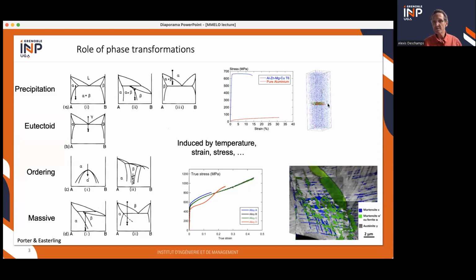Just two examples. If you make nanoscale precipitates, these are very efficient obstacles to dislocations, and you can increase, for instance, in aluminum alloys, the yield strength by large amount. And in steels, if you're able to monitor precisely the martensitic transformation of metastable austenite during straining, then you're able to have good combinations of strength and ductility with respect to more traditional grades.